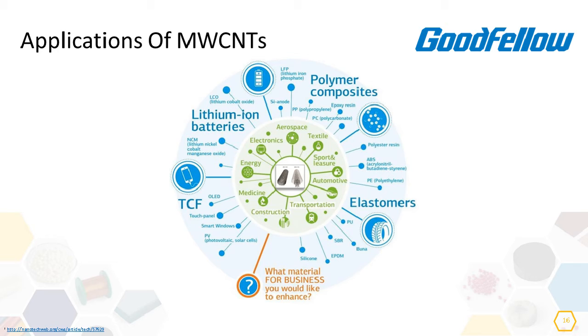Due to their electrical properties, as they are extremely sensitive to the effects of charge transfer, they can be used in sensors to detect, for example, gases, such as flexible hydrogen sensors, for which single-wall carbon nanotubes and palladium nanoparticles have been used. Also, due to their electron transfer capabilities, they can be used as electrodes, an alternative to graphite, as we discussed, for example, in lithium-ion batteries. In addition, due to their electrical conductivity and their shape, carbon nanotubes can be used for field emitter displays, as they have been found to have higher brightness emission at lower voltages compared to tungsten filaments that we are using at the moment.